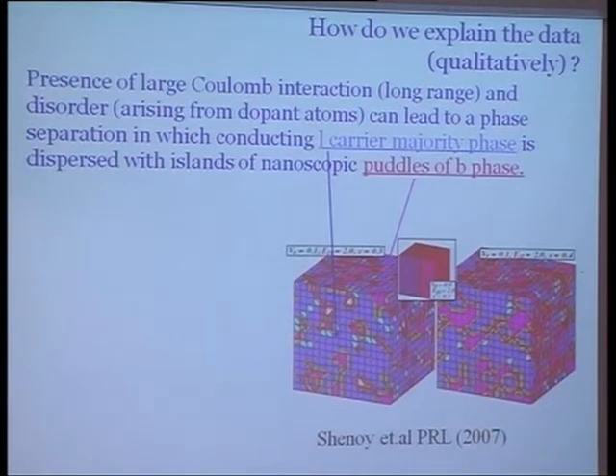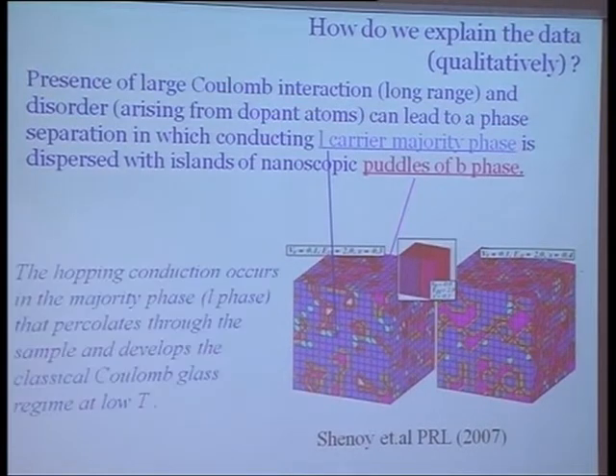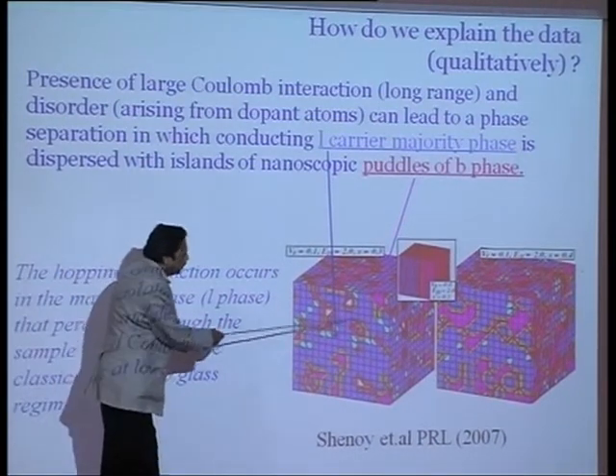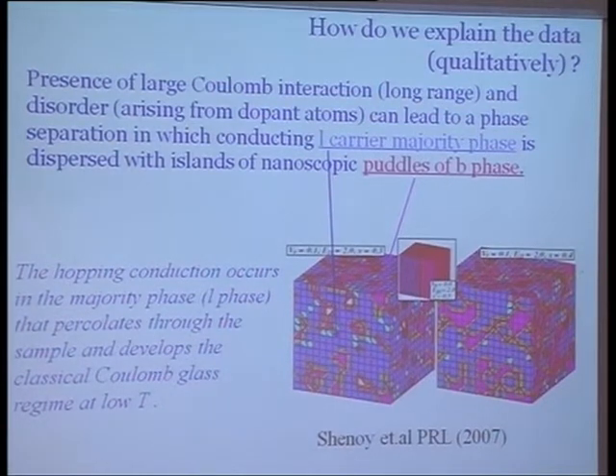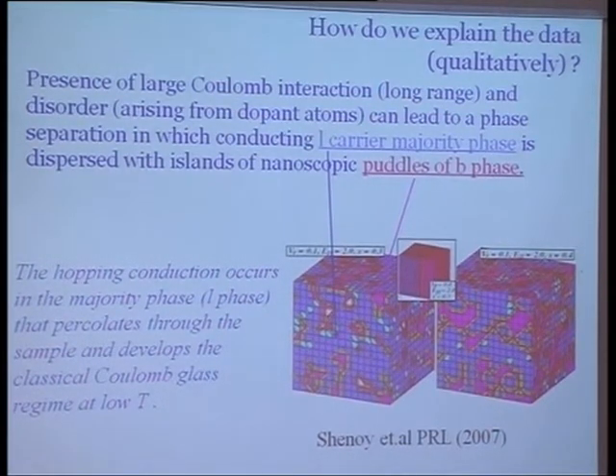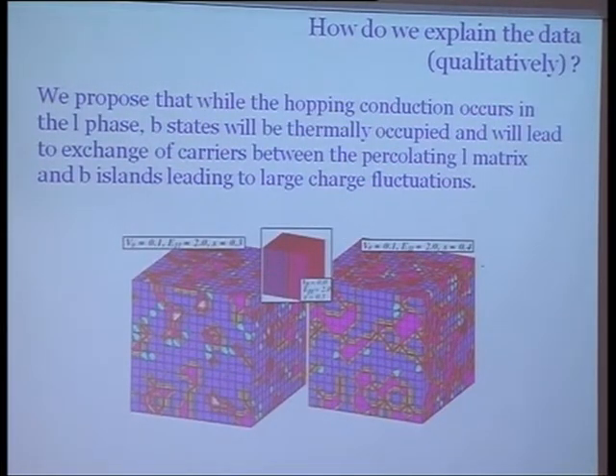and you get the metallic state coming in. So if I use this picture, then it is rather interesting to see how the noise can come into that. The important point is that the hopping conduction occurs in this localized phase. Even in the majority phase, there are clusters which are of finite size, and there is a variation in the cluster size. So what we propose is that while the hopping conduction occurs in the localized phase in the ferromagnetic insulating state, we can have carriers excited to the B phase by thermal activation, and there will be exchange of carriers between the two phases.